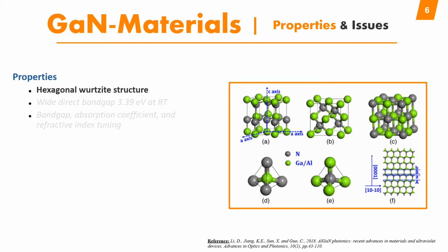For example, as we see here in this figure, the structural arrangement of these materials can come in three different forms: the hexagonal wurtzite, the zinc blende, and the rock salt. The most stable among all these at room temperature and ambient pressure is the hexagonal wurtzite, where each gallium atom is surrounded tetrahedrally by 4 nitrogen atoms, and the same for nitrogen. Each nitrogen atom is surrounded by 4 gallium atoms.